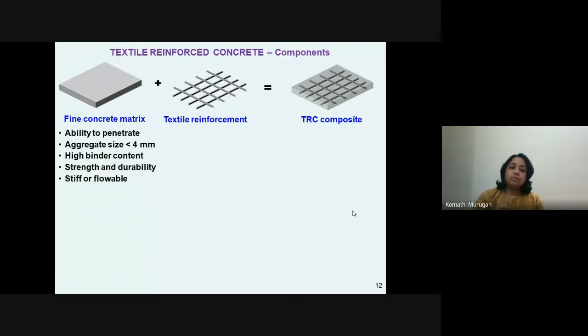Looking into why this matrix is a fine concrete or a fine grain matrix, this matrix should have the ability to penetrate between the grids of the textiles. The textiles, what we talk about, have grid dimensions of, say, even 0.4 or 0.5 mm width. That is the size of the grid through which the concrete should penetrate to fill the section, maybe even as less as 0.4 or 0.3 mm.